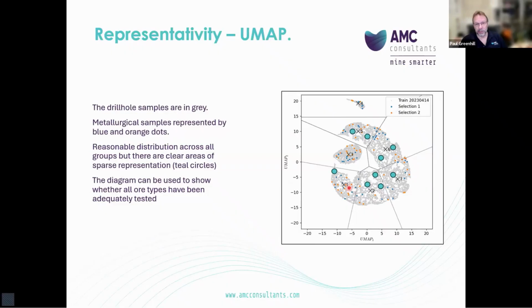So how do we use this, and what can we get out of it? So the dimension reduction plot enables us to visually represent where metallurgical samples exist within the multivariate space. Because the metallurgical samples themselves have the same characteristics, the same measured data as we have used to generate the UMAP, we can plot those samples on the UMAP projection. And what you can see here, where we have plotted two selections, selection 1 and selection 2, metallurgical sample sets, is that they actually broadly cover the UMAP space.